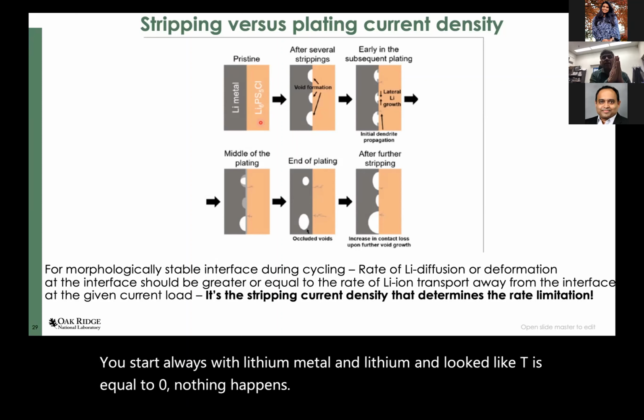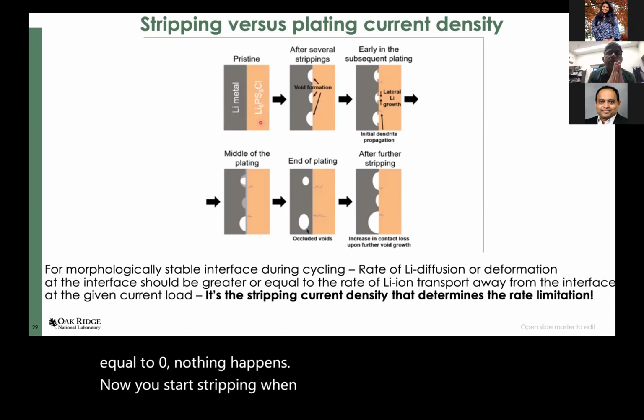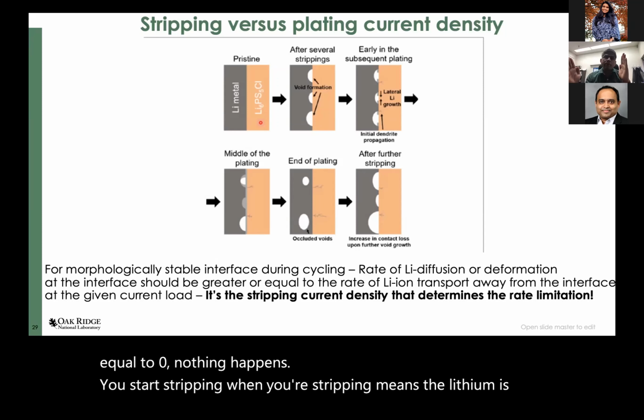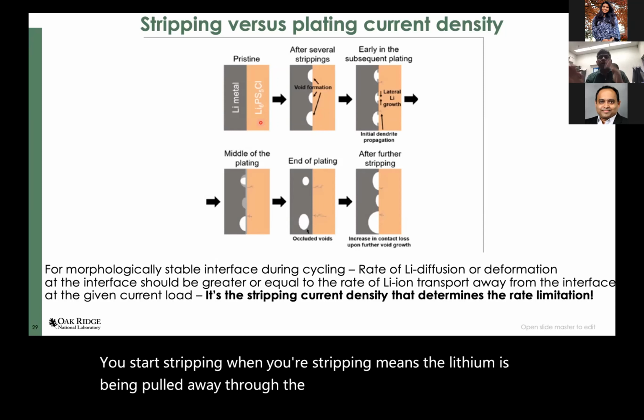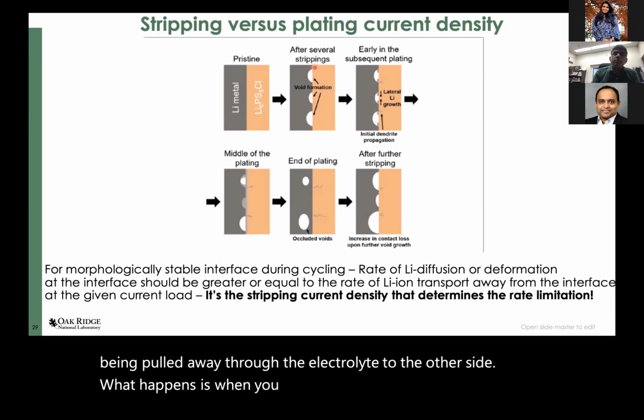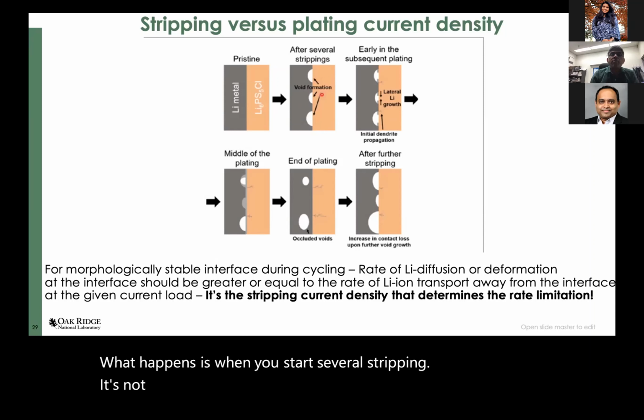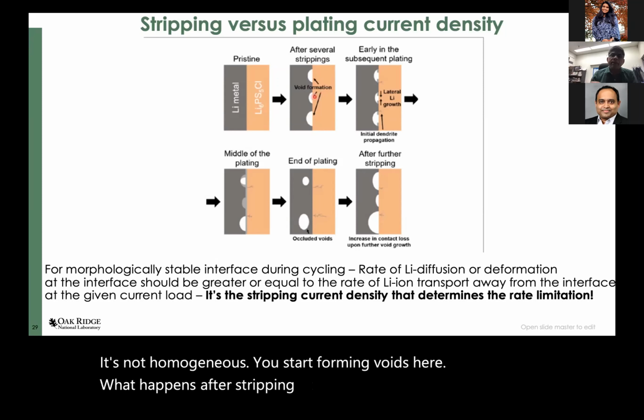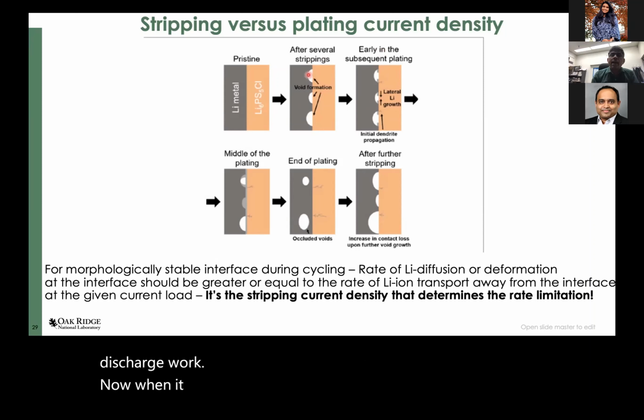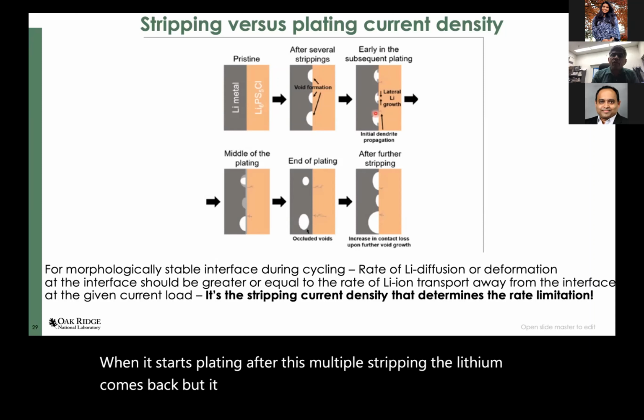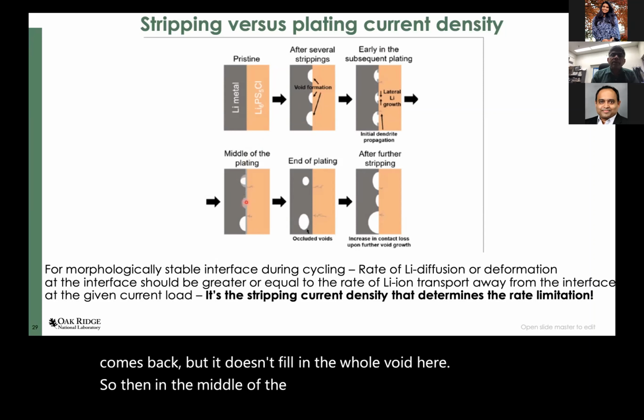Now you start stripping. Stripping means the lithium is being pulled away through the electrolyte to the other side. Now what happens is when you start stripping, it's not homogeneous. You start forming voids here. Now what happens after stripping is plating, right? That's how charge discharge works. Now when it starts plating after this multiple stripping, the lithium comes back, but it doesn't fill in the whole void here. Okay. So then in the middle of the plating, you can see this is happening.